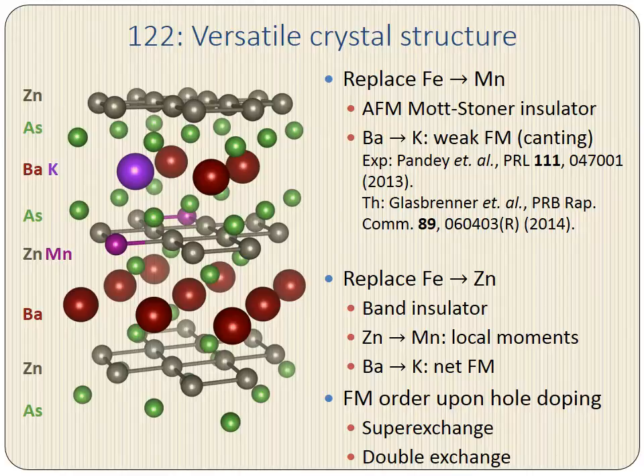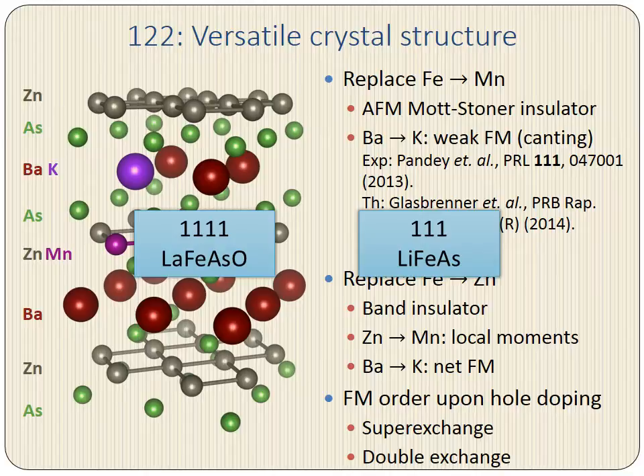Before moving on, I want to again emphasize the versatility of the crystal structures common to the iron-based superconductivity field. Beyond the 122 structure pictured here, there are several other classes, such as the 111 and 1111 classes, all of which have this planar iron arsenic structure. These structures in general hold up very well to the swapping out of one atom for another. So zinc has successfully replaced iron in both the 111 and 1111 cases with the prototypical examples that I have pictured here. In all cases, they are band insulators. So within this entire class of iron-based superconductors, we have a rich collection of new potential DMS materials to explore. And even better, we can bring our knowledge from the iron-based superconductivity field and apply it to these materials.